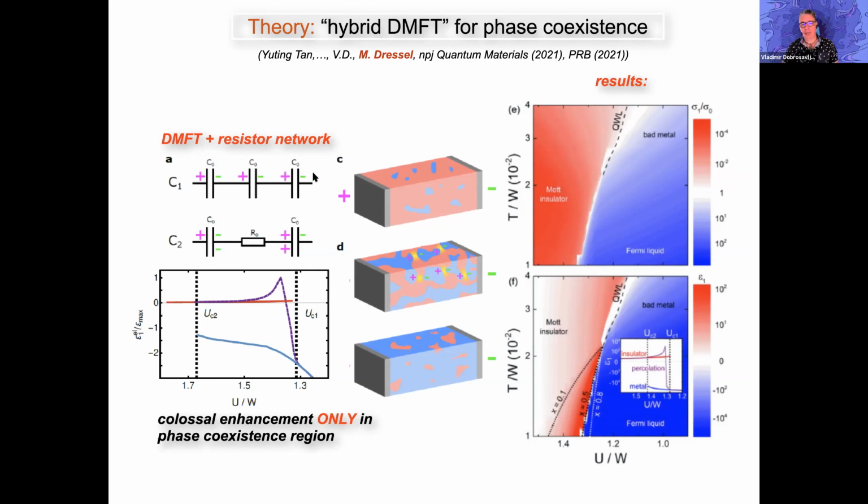You see now when you apply an electric field, this entire region is now polarized, and it has a much larger dipole moment. If we make these metallic regions bigger, then the dipole moment that is formed is larger and larger. And this creates a huge polarization and a huge dielectric constant, as long as these regions still don't connect.